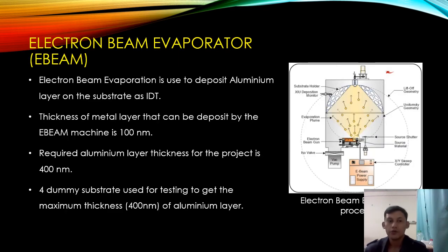For my project, I will use an electron beam evaporator to deposit an aluminum layer on the substrate as IDT. The thickness of metal layer that can be deposited by the EB machine is 100 nanometer, and for my project, the thickness of aluminum required is 400 nanometer. Before I deposit the aluminum layer on my SAW device, I will test on 4 dummy substrates.